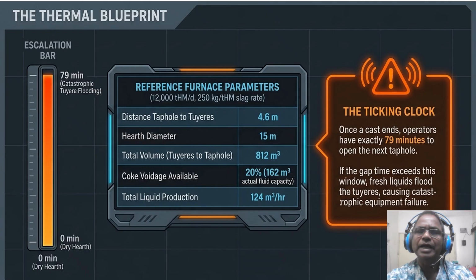We manage the gap time to preserve the tuyere, but a flooded hearth does more than just melt copper. It shifts the furnace physical mechanics. When liquid rises too high, it triggers a mechanical disaster known as an ejector choke. So what is that ejector choke mechanism? So follow the transition from panel A to panel B.